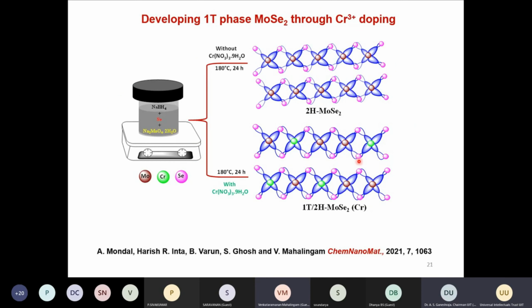So continuing on this, we thought, is putting organic inside them the only way? It's not a very good idea. So we thought, is there any other way to do this? And then we came up with the idea that chromium doping will help, because chromium can have one more electron which can fill in that t2g. I hope you remember that in the octahedral symmetry we have one electron less in the lower t2g orbital. So if we have chromium inside this material, this time we took MoSe2.